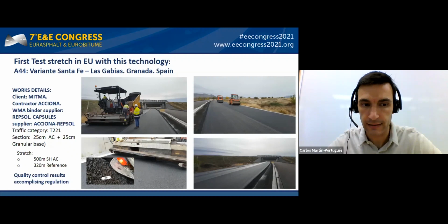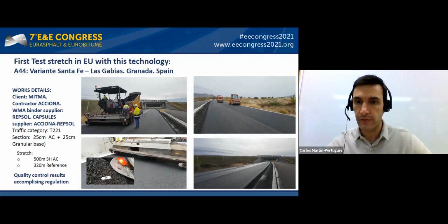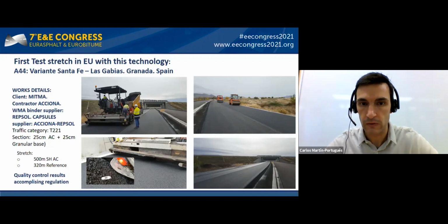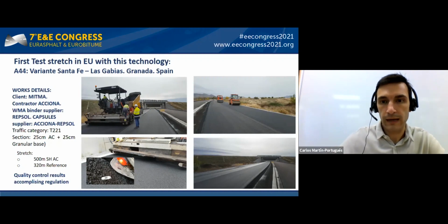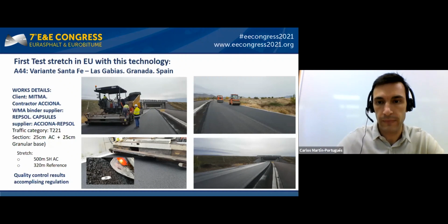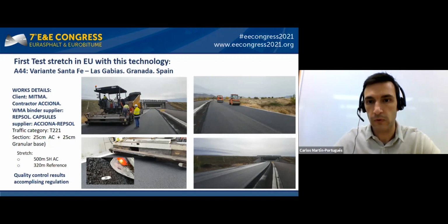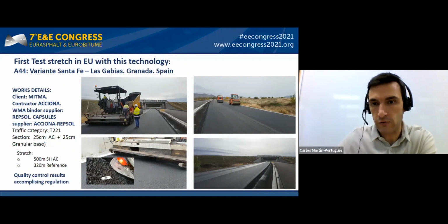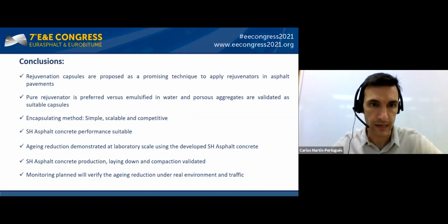We undertook the normal quality control, and everything accomplished the regulation, so it was quite satisfactory, and also the works were quite good, in terms of laying down and compaction, without any remark. So with that, we can conclude that the results were as expected, and we are just waiting for the exposure to real environment and the real traffic to verify that the good results at laboratory scale are confirmed under full scale traffic and environment exposure.